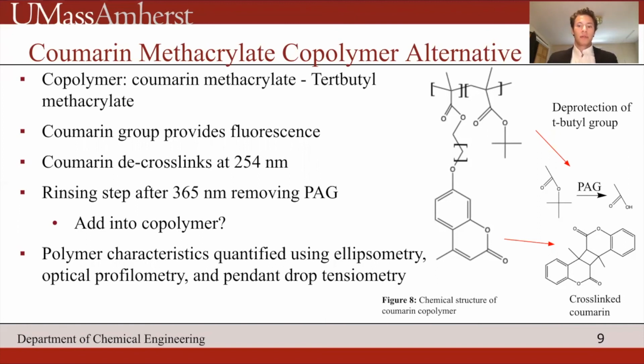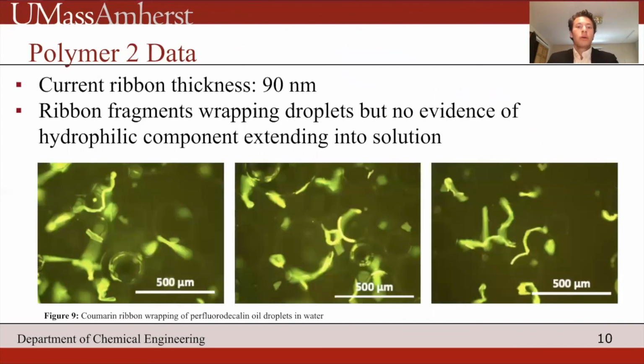Polymer characteristics are being quantified using ellipsometry, which is able to measure the thickness of polymer films, optical profilometry, which is able to measure the dimensions of polymer ribbons, and pendant drop tensiometry or contact angle measurements, which provide us with an understanding of the degree of hydrophobicity or hydrophilicity of the protected and deprotected groups, respectively. We're currently able to create 90 nanometer thick ribbons that are able to successfully wrap multiple droplets, but at this time show no evidence of the hydrophilic component extending into solution, which we hypothesize is due to PAG being rinsed off. Since the PAG is rinsed away, there is not as much of a hydrophilic component, so it does not extend into solution.